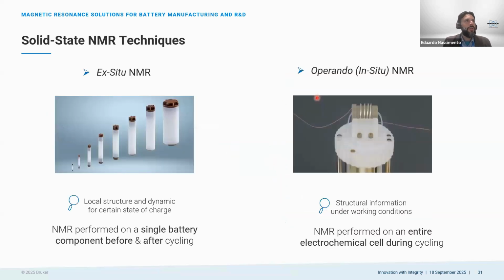We have basically two types of solid state NMR that we normally apply for battery analysis. The first is the so-called ex situ NMR. Here the idea is that you create your batteries, or even start by analyzing your raw material. But the other point is that you create your battery cell, you do your cycling, and then you open your battery cell and extract all the components that you want to analyze, put them in this rotor, and then you do the analysis. The other is operando NMR, where you create your battery cell inside the NMR probe, and then you bring that to the NMR instrument and you do your cycling and NMR in real time.